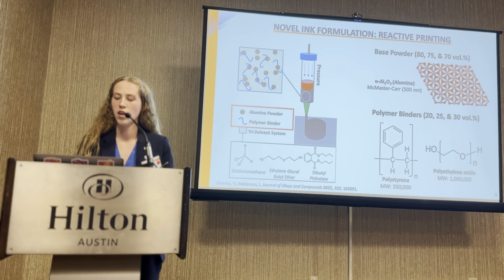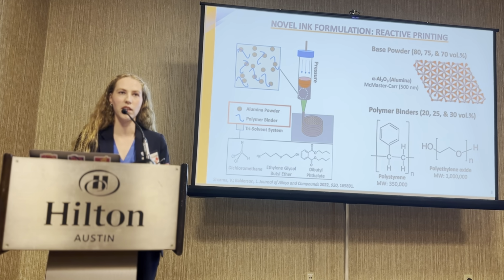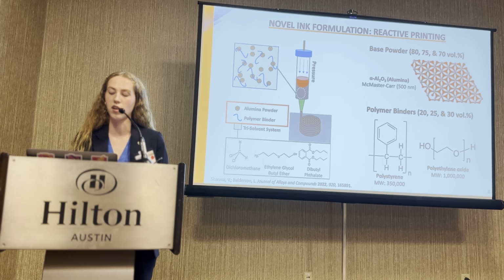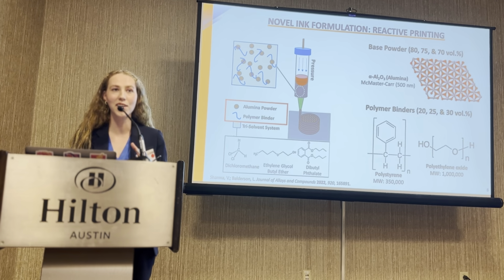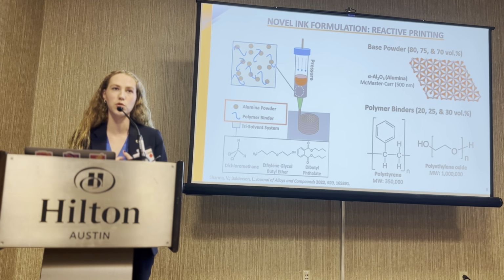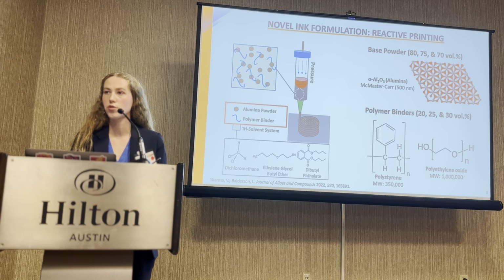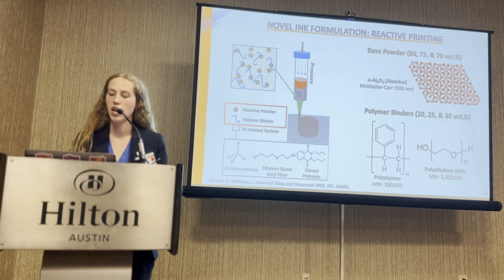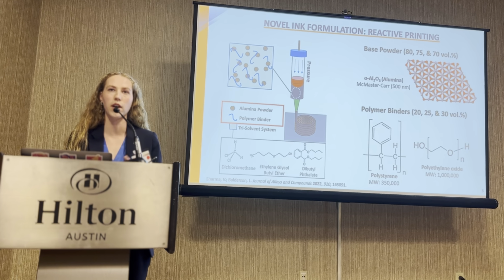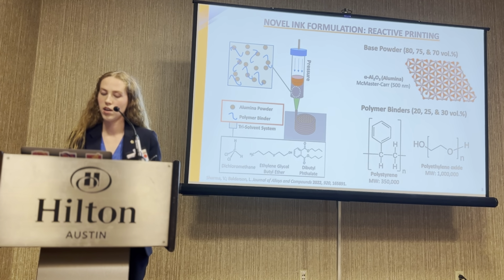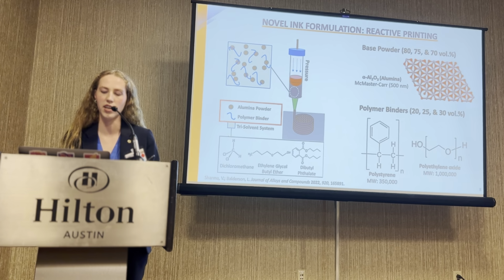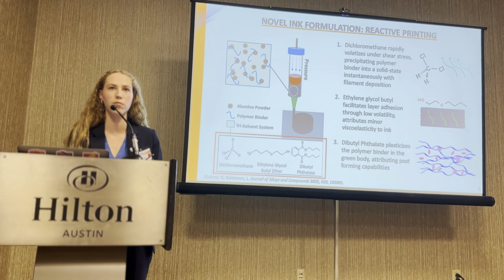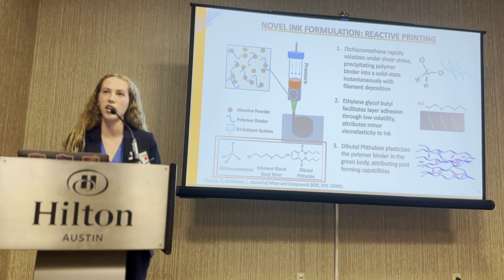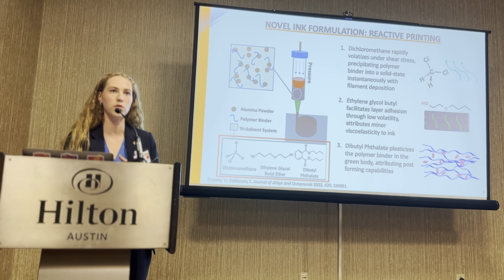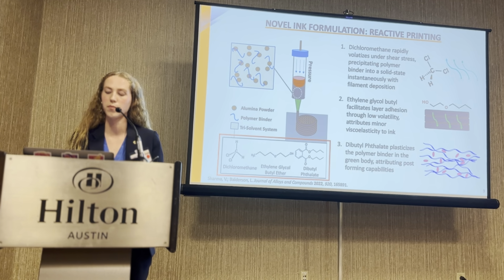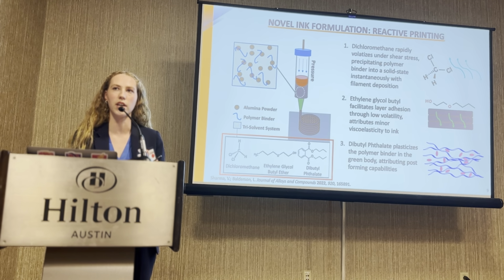As you increase the volume percentage of the alumina powder, the ink becomes crumblier and it's harder to extrude from the nozzle. Then the polymer binders, as mentioned before, polystyrene or polyethylene oxide, they act like the clay or putty to hold together the ink. They create the ink's shear thinning properties. They have high yield stress, which makes it act more like a solid when printing, and it has a higher storage modulus. They also provide more of that shape support when sintering. And the trisolvent system, the third component of the ink, has dichloromethane to volatilize under shear stress and allow that ink to set as it prints, the EGBE to make the ink self-healing and adhere the layers, and the DBP to enable that folding behavior.